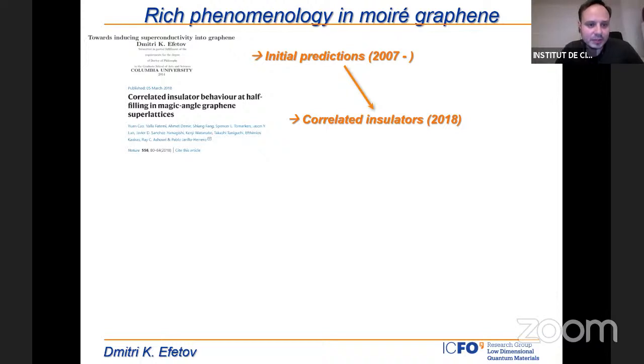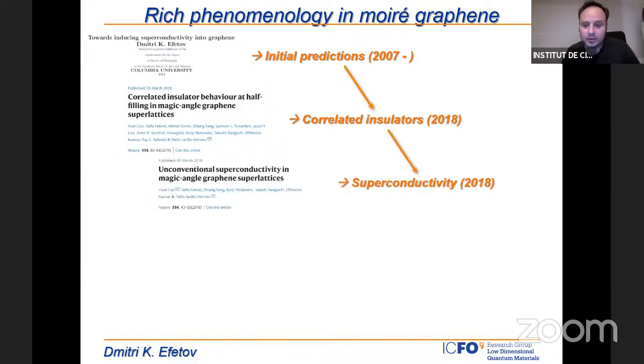And then basically what happened was a revolution introduced by Pablo Jarillo-Herrero at MIT, who in 2018, all of a sudden, unexpected to everybody, showed that two graphene layers, if they're twisted in the right way on top of one another, can actually start having strongly interacting electrons. His first work was on correlated insulator behavior at half-filled graphene devices. Then nearby, he immediately also observed that these same type of devices can be superconducting. So he observed strong correlated insulators and superconductivity close to it.